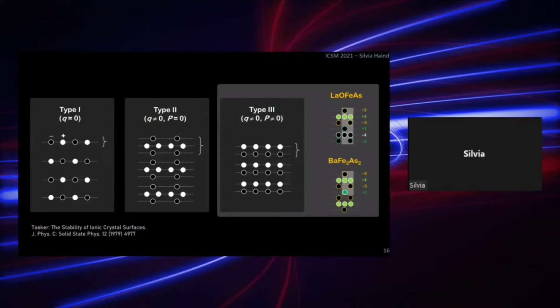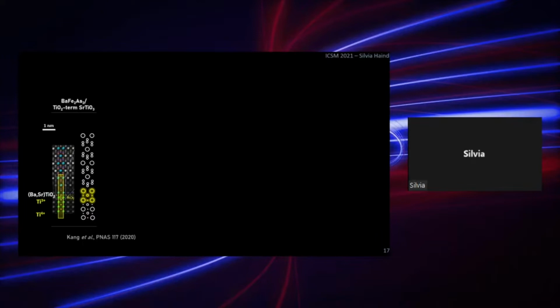So with that knowledge, we can go into the literature and search for different iron-pnictide heterointerfaces which have been studied. And we found a couple of examples, for example, the barium 122 on STO. And here we have to face two different terminations. So here is the titanium oxide terminated STO, and the barium 122 is grown on top of it. And you can see here we have a unit cell of a mixed barium strontium titanium oxide interface layer which forms. And what is also seen, it was also reported that the titanium valence changes from 4+ to 3+ when we go towards the interface.